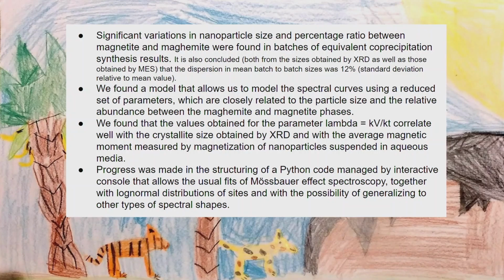We found a model that allows us to model the spectral curves using a reduced set of parameters. I think that this is important. It's a way to have an identification of the Mössbauer pattern with some values. In that case, the values are the lambda, the mean lambdas, each mean lambda, also the whole mean lambda, and the relative fraction between the two contributions.